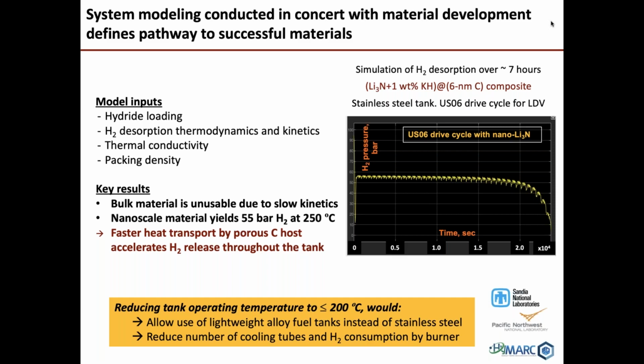And it will predict the temperature in the tank. It will predict the rate at which the hydrogen is released in real time. And you do this with a realistic drive cycle. The one shown here is called US06, and it's a fairly standard drive cycle for light-duty vehicles, and actually a fairly strenuous one. And what we have to do to get to this point is experiments that provide the hydride loading. This was a lithium nitride material that is hydrogenated to make lithium amide, and it's in a porous carbon.